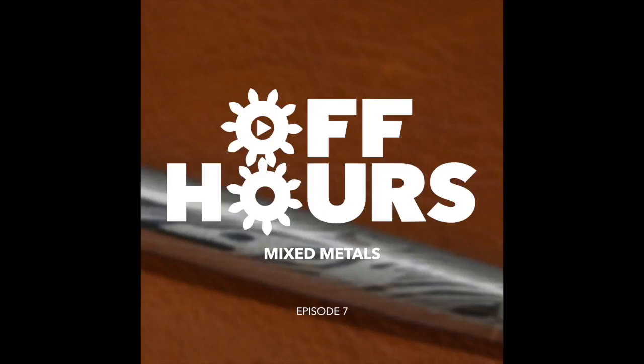If you don't do that, when you do eventually cast, those little air bubbles have left a pocket that's attached to the part. And so you end up with these little tiny balls of metal that are attached to the edges of your pieces. And sometimes they're in the most inopportune spot, so they'll destroy a pattern because they've attached to the workpiece that you've got. Dealing with air and air bubbles is kind of an important thing when you're dealing with casting, not just when you're pouring the metal, but also when you're making the mold to begin with.